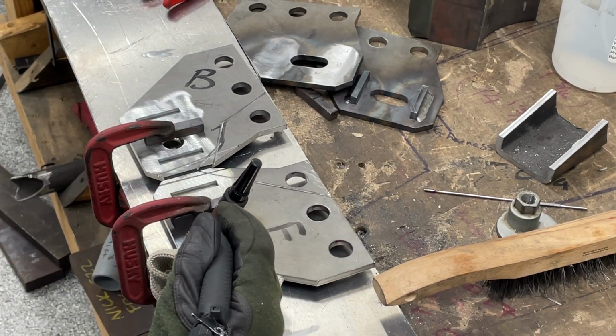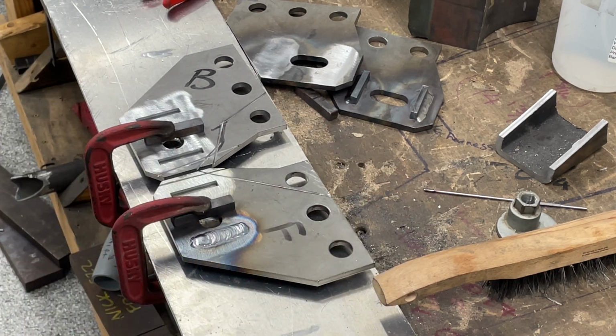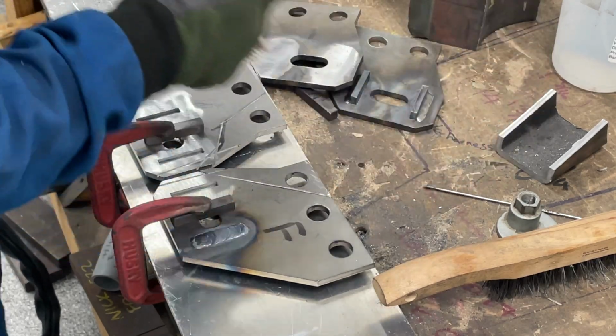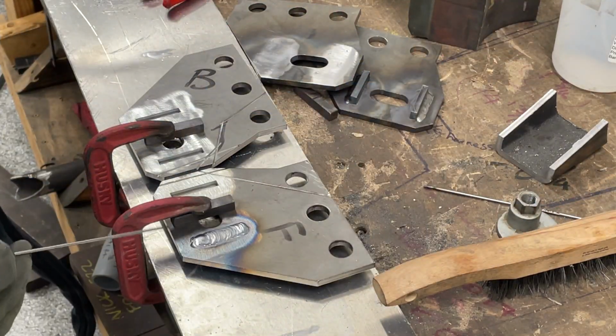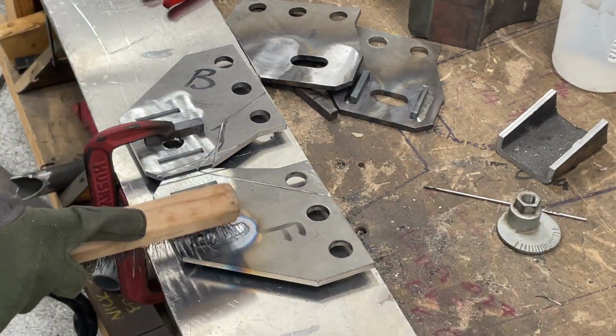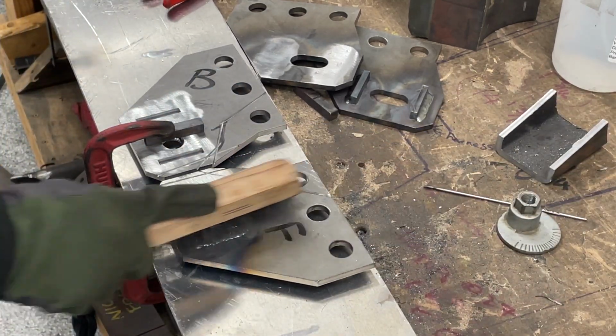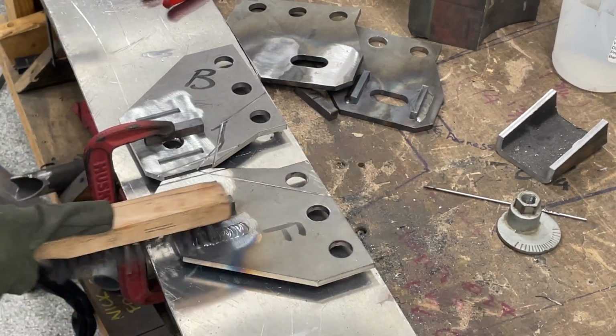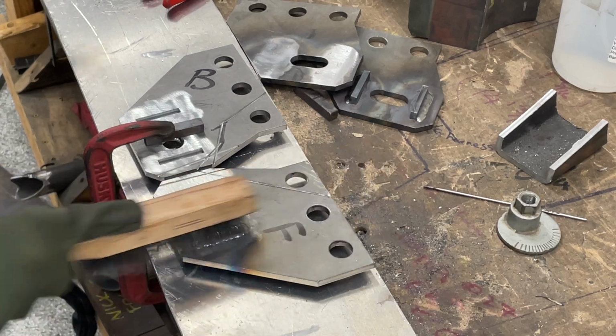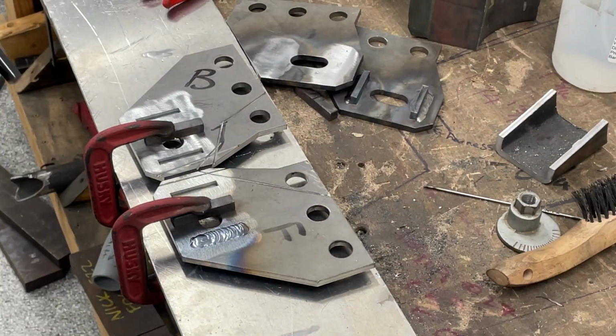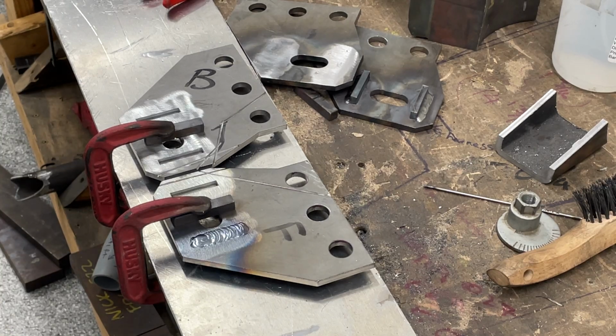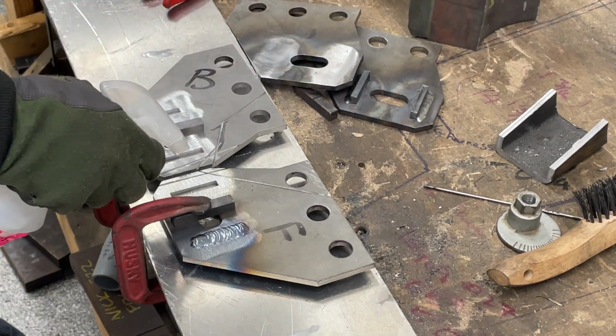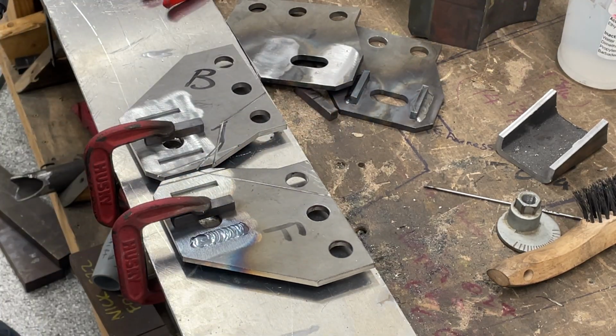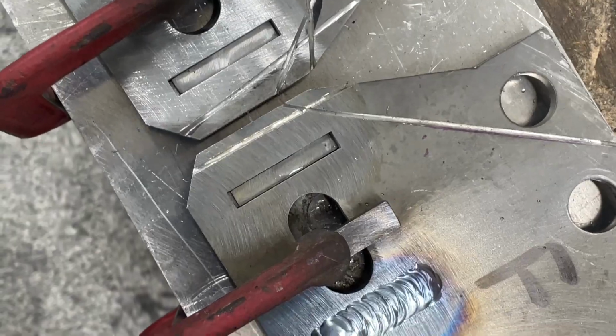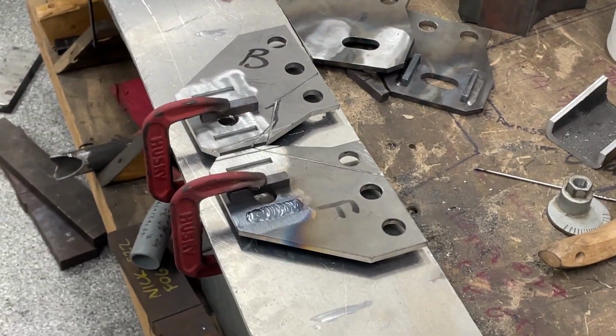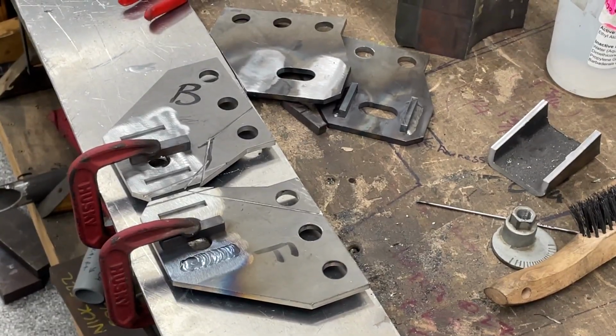While it's glowing red hot, you can use the argon to help prevent that oxidation from getting too thick. You can see these little tiny black dots on the surface here. Those are silica beads from the welding rod. There's a lot of silicon in 70S2, and it helps with wettability, the material getting wet. All right, we finished welding this one, and it has been welded with a good preheat and a high interpass temperature. Now let's make sure the other side of this is okay. Good, it is evaporating water, kind of. The material at the very bottom of it actually still has water, which means it's below 200 degrees, or the boiling point of water. So let's heat it up so we can get that to evaporate.